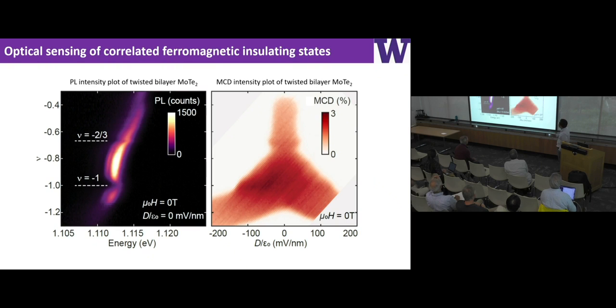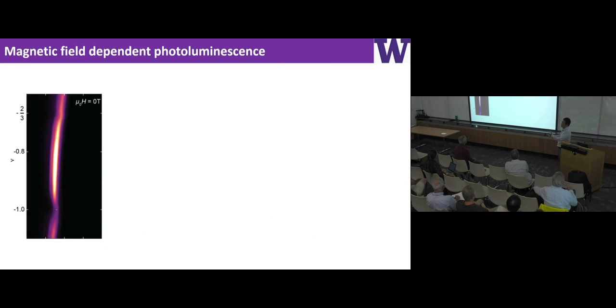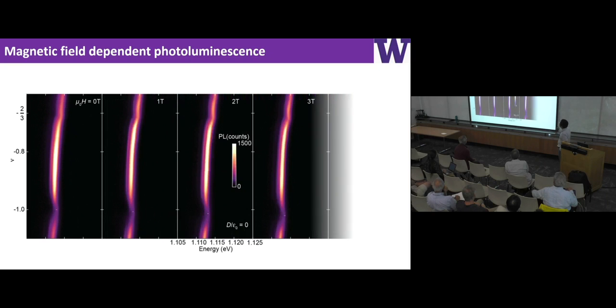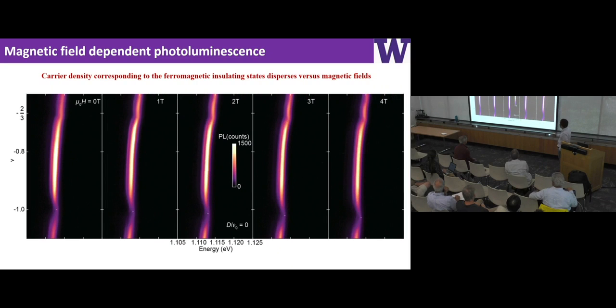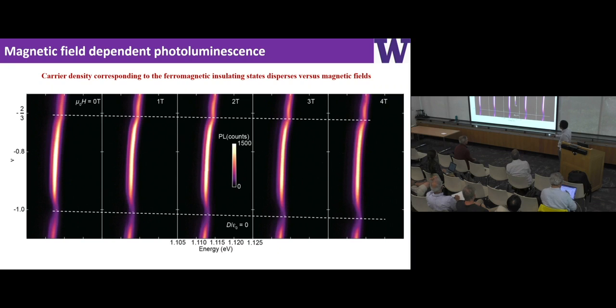Then we can compare this luminescence intensity plot to my MCD measurements. You can clearly see that whenever there's a gap state, we see an enhancement, a little bump, in the MCD signal. From this kind of comparison, we can establish that we have ferromagnetic insulating states. The next step is to do the same measurements at different magnetic fields, from 0 Tesla all the way to 4 Tesla. If you look at the carrier density corresponding to this -1 filling, you will see that it actually changes with the magnetic field.